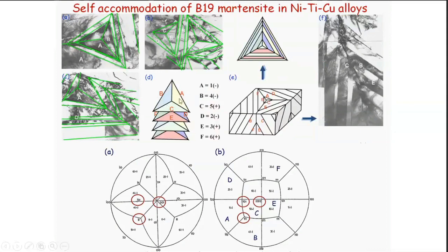To see that, you have these 3 plates stacked on another 3 variants which are stacked together, like when you put some straw hats, you stack them all together, how it will appear. And it becomes more clear when you section them along a vertex. You can see chevrons along the thing. So you see this chevron structure along one side. So this is a very interesting arrangement where you've got 6 variants coming together and having a very common axis. This is the one common axis that you have. And what they try to do effectively is to give rise to self-accommodation, that is minimizing the strain felt by the parent phase. So that is self-accommodation.